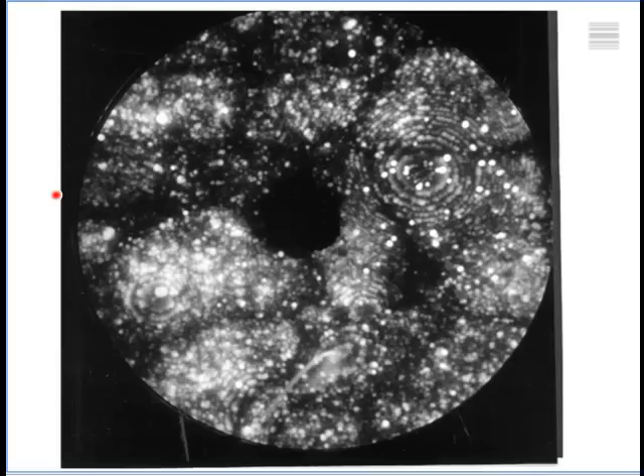Now, if you notice, there are some dark lines here, okay? And what's happened is that by severe deformation, we have made the crystal size extremely small. So this is a few hundred atoms big. So by introducing grain boundaries on a very fine scale, we have a strength of 5.5 gigapascals.